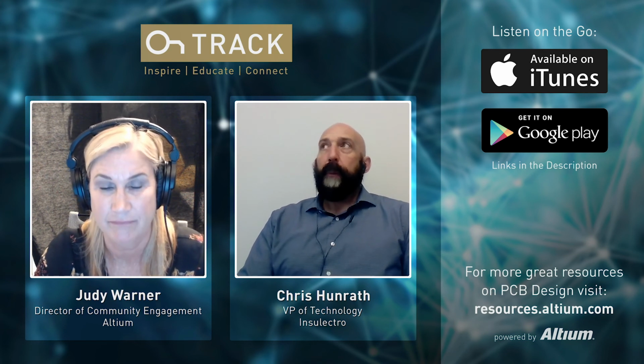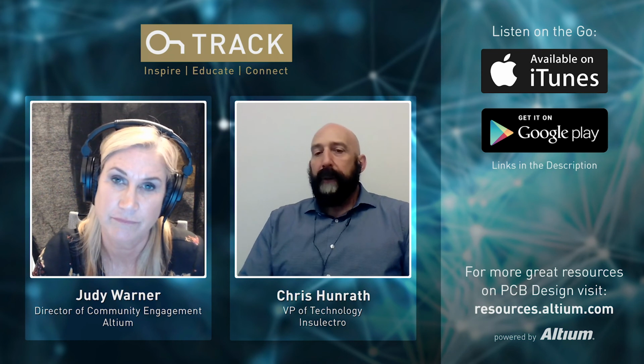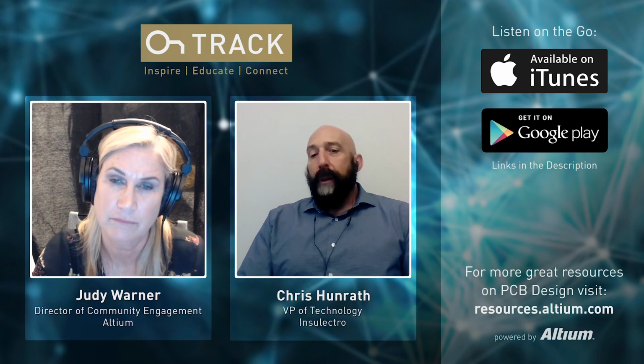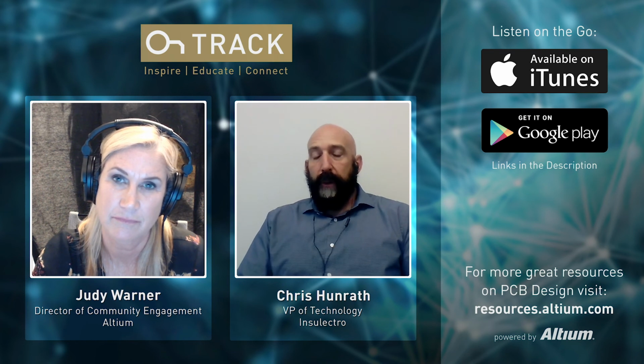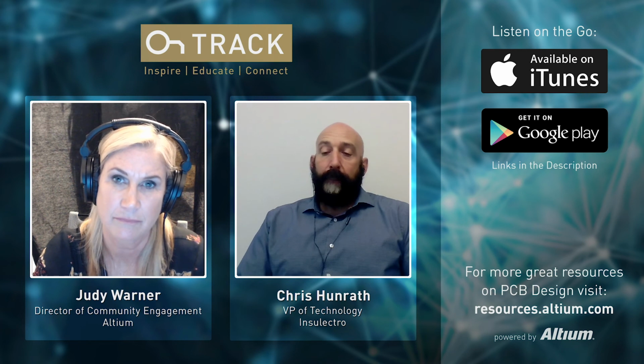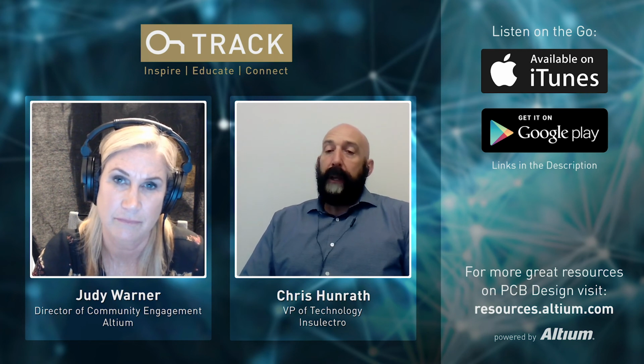There was a really good paper put out around 2011, 2012 at IPC that showed just how long it takes for the moisture to get around, because if you have strip line construction, or if you have a reference plane in RF design, the moisture's got to go around that copper plane. It can't go through it, and I've seen people underestimate the baking and end up with scrap for no reason.